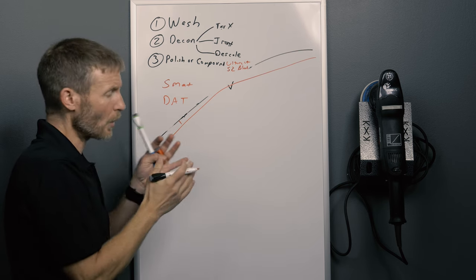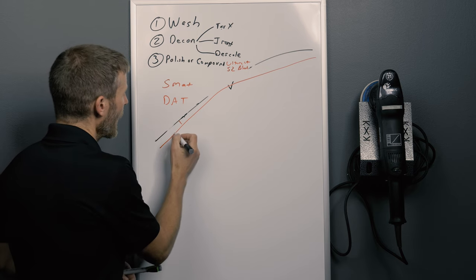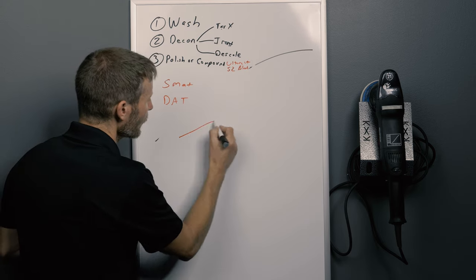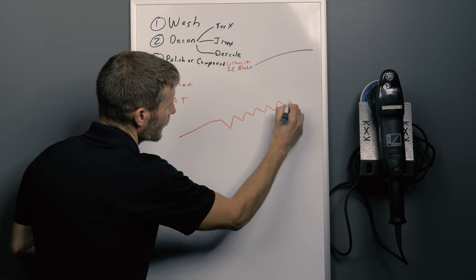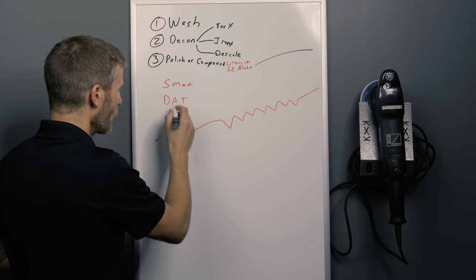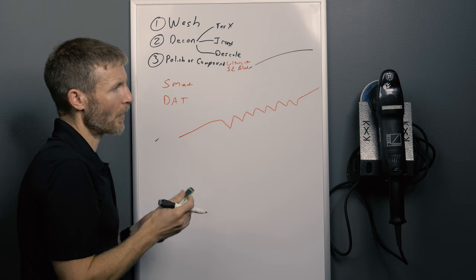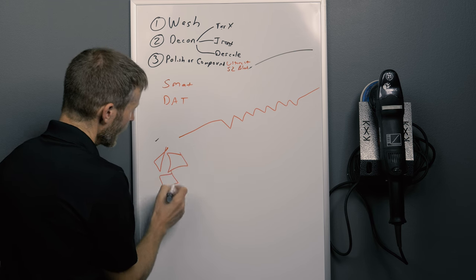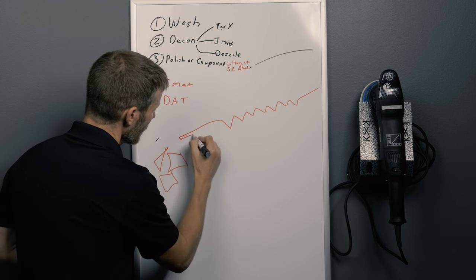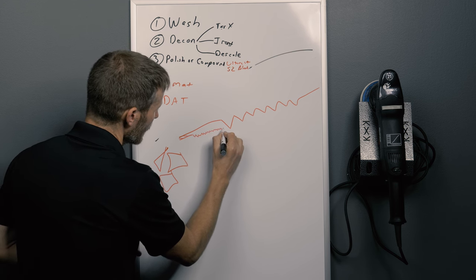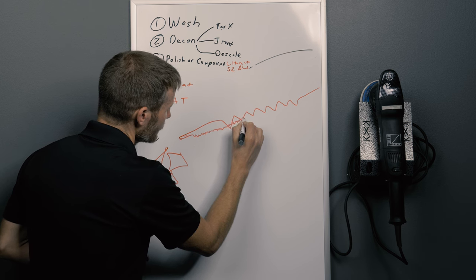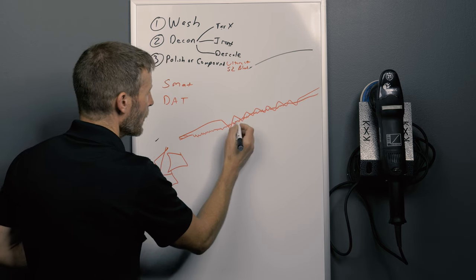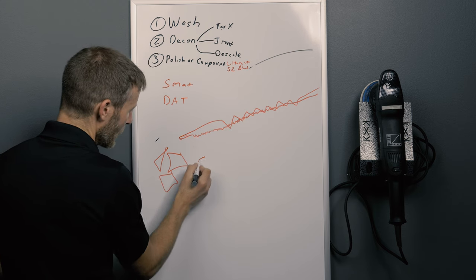Anyways, you use one of these compounds, you put it on a polishing pad, you take that machine, and what it's going to do is rub that liquid solution with the abrasives in it, and slowly level the paint. If you already use something too aggressive, or what used to be termed rocks in a bottle, then as your, say you had a surface with swirls here, lots of swirls all in it, and you were to come along with your really heavy, aggressive compound that had big abrasives in it, that are like jagged abrasives. Those jagged abrasives, as they come across, they're going to level this, but they're going to leave it like this. Not as bad as it was, but they're going to still leave what you call micromarring or whatever term you want to use.